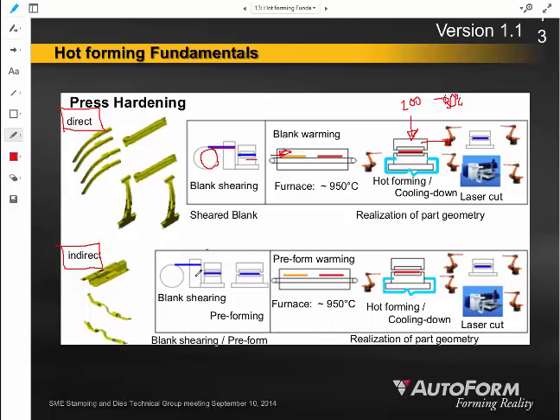Indirect hot forming starts off with the same operation, but instead of going directly from the blanking operation into the furnace, you can actually form that material some of the way, partially, at room temperature. That's going to allow you to make a slightly deeper part without necessarily having a high degree of localized thinning. Right? One of the problems with forming these materials at such high temperatures when we do this direct hot forming is the fact that any thinning that does happen tends to be highly localized.